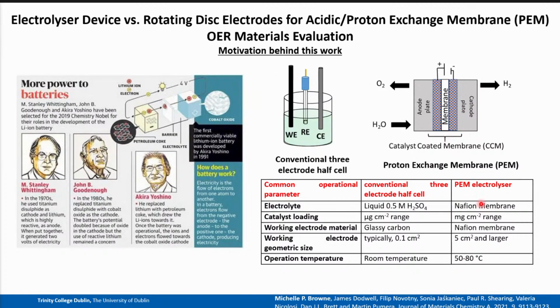And then the feeds that you put into it, the liquid feed, is water. The catalyst loadings differ significantly. The working electrodes that we use in the 3-electrode cell is made of glassy carbon. So glassy carbon itself actually corrodes and pits under acidic conditions. So if you continuously use this material to evaluate your catalysts, you will even get changes in the active surface areas because of the pitting, but most people won't realize.